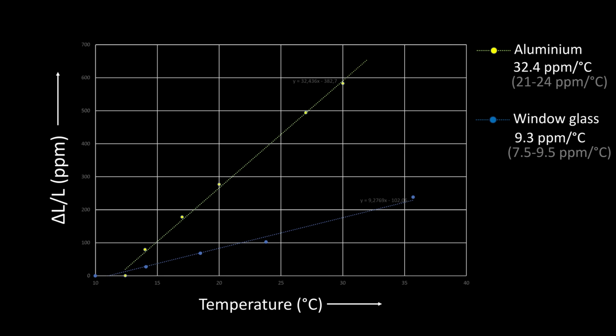The graph for window glass is shown in blue and results in a CTE value of 9.3, which is also a bit on the high end of what we expect. But I guess it's still within the range that we can expect. So here the experiment more or less matches with the known value range.